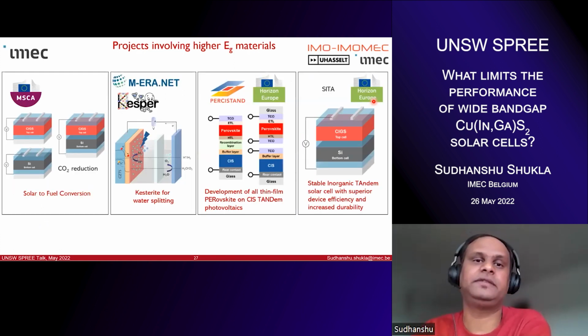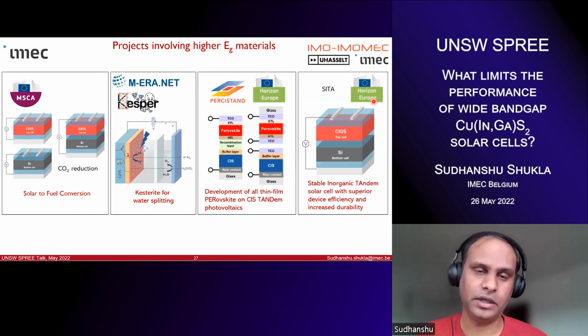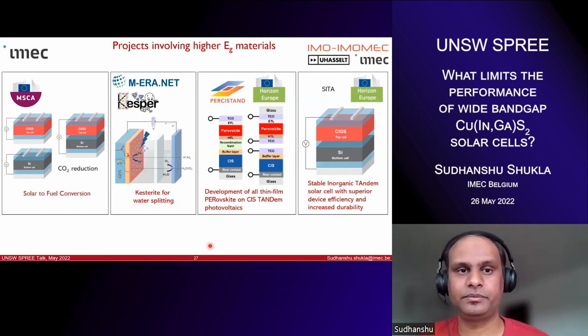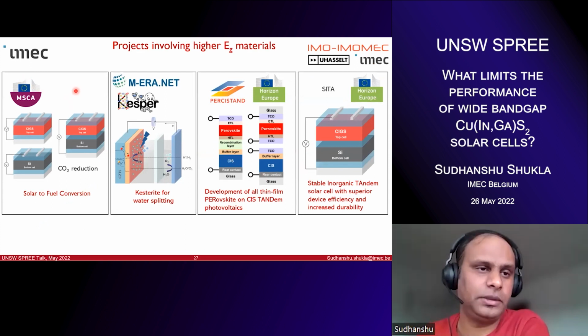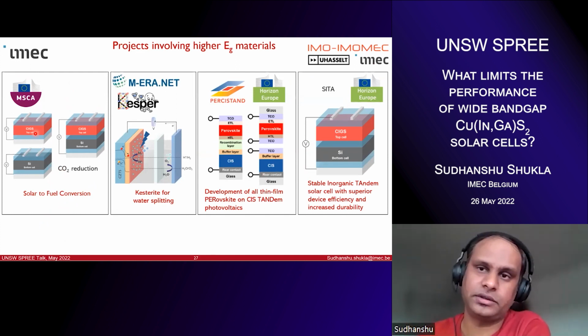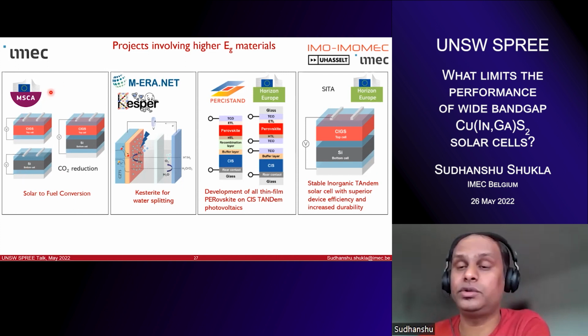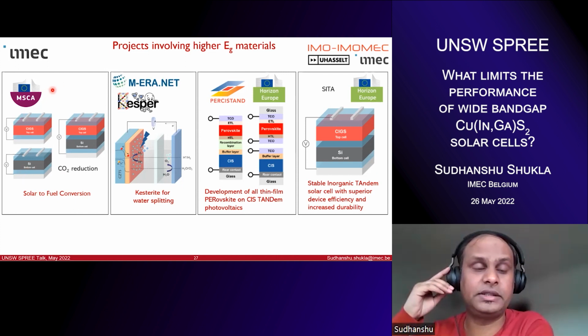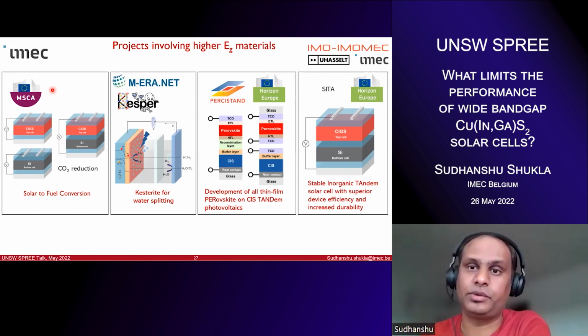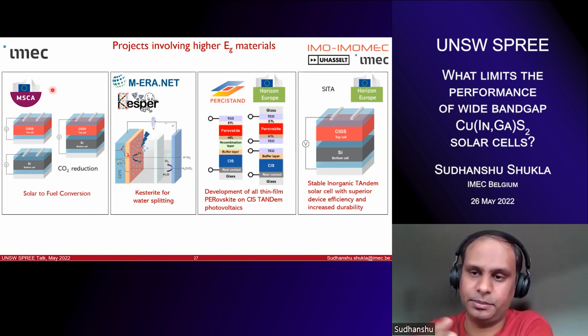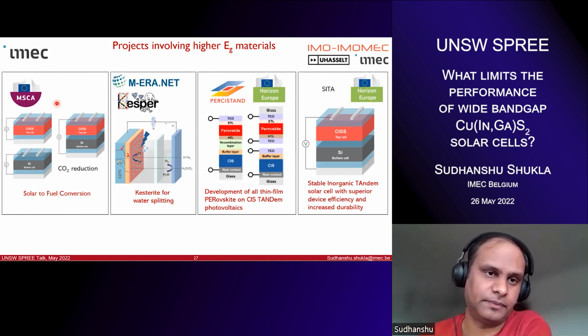So we spurred some activities at IMEC when I joined here. I was involved in several project proposals here, for example, one that I recently received as a Marie Curie postdoc fellow, and that is on solar to fuel conversion using wide bandgap CIGS, and the bottom cell, that is silicon, to drive CO2 reduction, for example, because you can make the CIGS wide band gap, 1.7 eV or 1.8 eV, depending on how much gallium you put. This could be quite a promising strategy to go towards other applications like CO2 reduction.